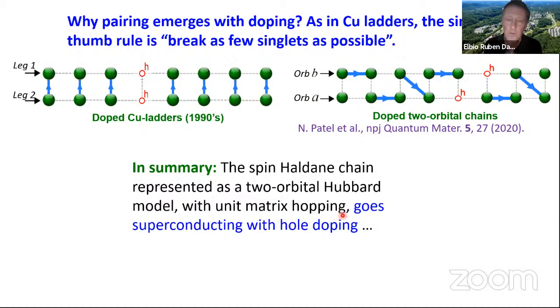That's a problem. Right now, with a postdoc at UT, Laurel, we are trying to analyze to what extent we can relax this approximation. Because in reality, in materials, if you have two nearly perfectly degenerate orbitals, very often the lattice will try to find a rearrangement of atoms that breaks the degeneracy. So we want to study what is the range of validity of everything we said with respect to the hopping matrix. So results will appear soon.